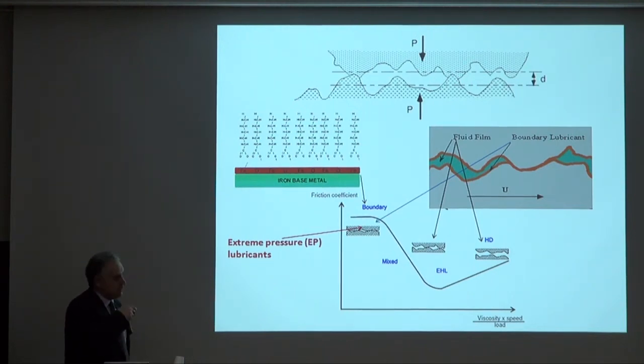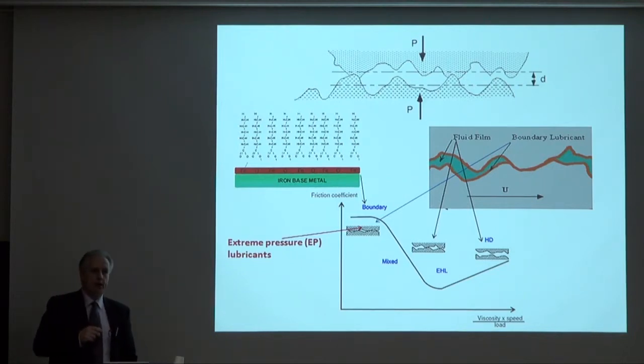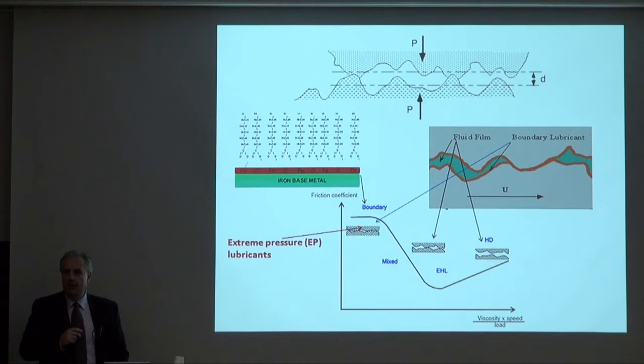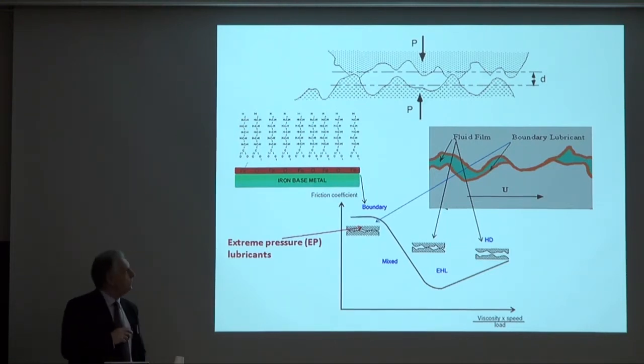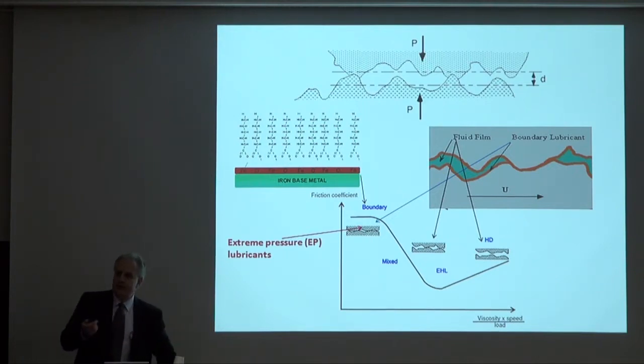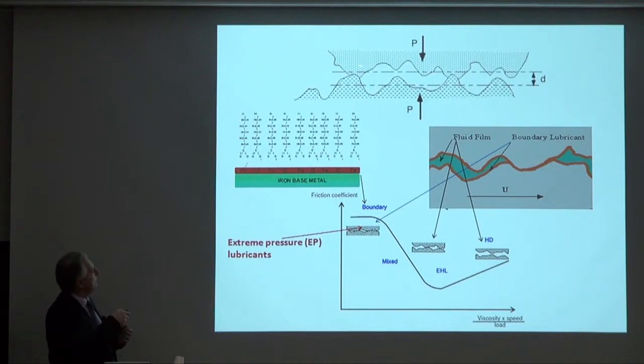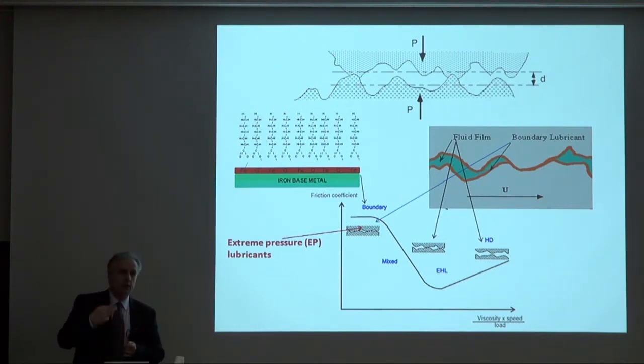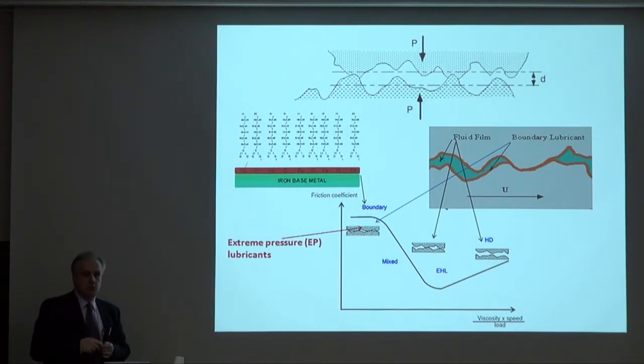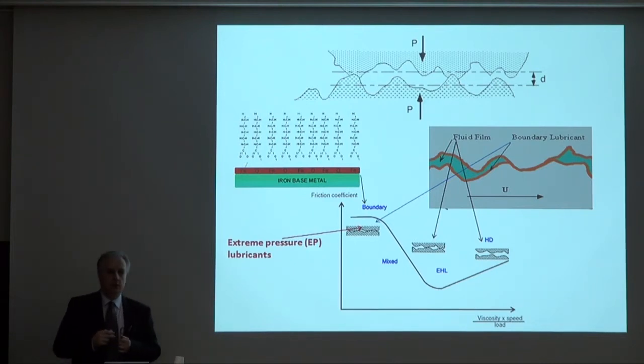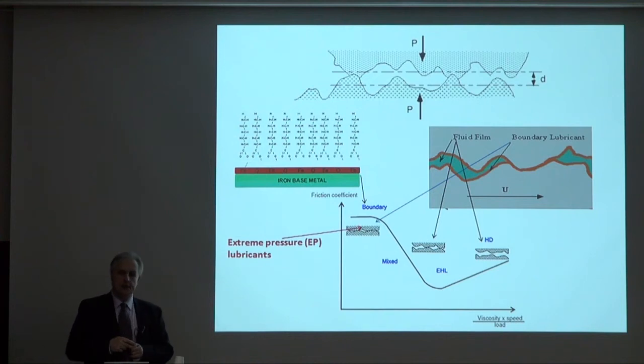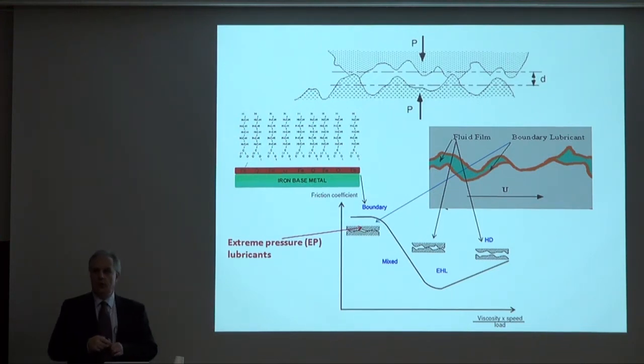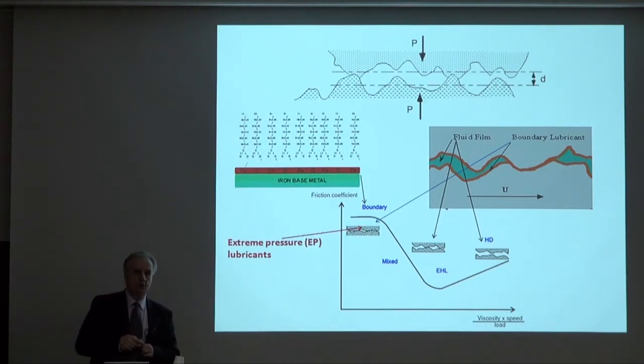If we add also a tangential force when we start sliding, you can see how easy it is to begin to wear out this material, and the process starts at these microscopic asperities where the two surfaces wear out. Then, of course, the gap will increase, and we have leakage in that seal, or we have vibrations in the bearing surface that has been roughened as these asperities are removed. But is this happening all the time in every system? In an engine, for example, where we have a piston that is reciprocating in order to induce the combustion process, does the piston ring, which is touching the inner wall of the cylinder, really interact continuously with the wall, or only at certain instances of a given stroke cycle?